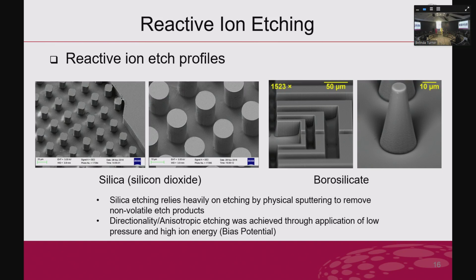So here is another picture showing, because in our node we are only processing the silicon substrate. We also can do silica substrate, so it's silicon dioxide, and also borosilicate glass. It's a little bit different here, because for the glass and the silicon dioxide, it's more physical. So we use ion bombardment to do the etching instead of chemical reactions. So it's a little bit different to the previous. The previous is more about the silicon, and here is more about the glass.